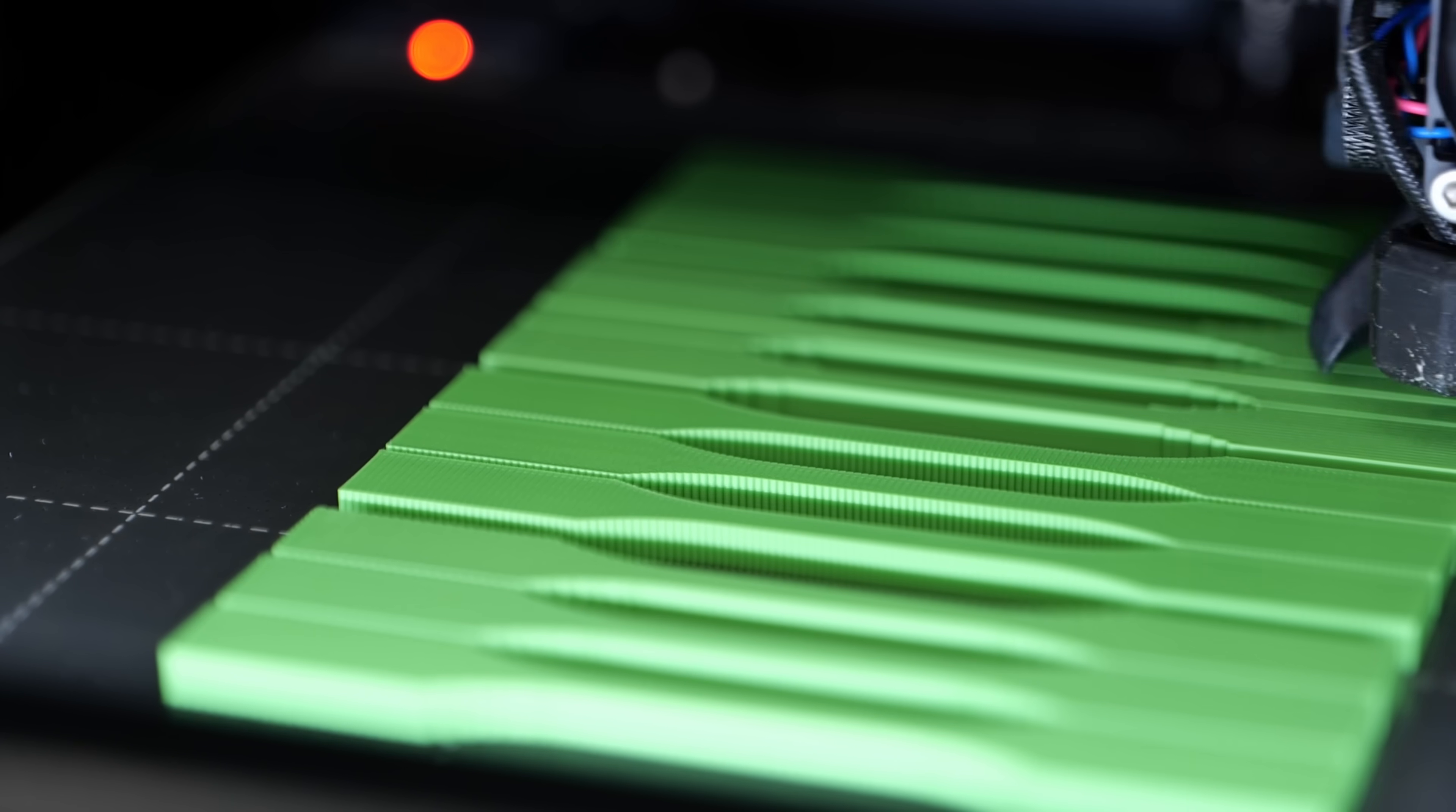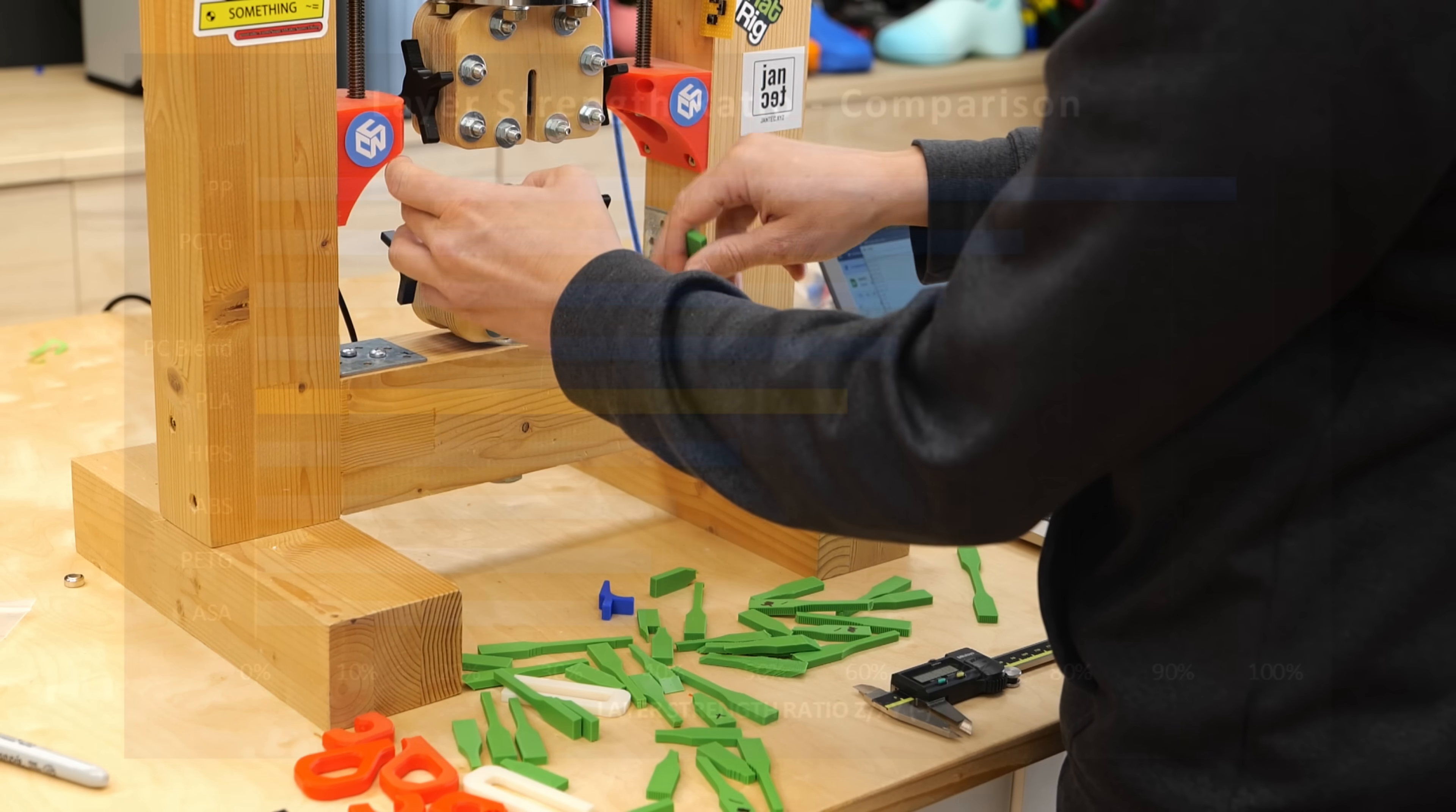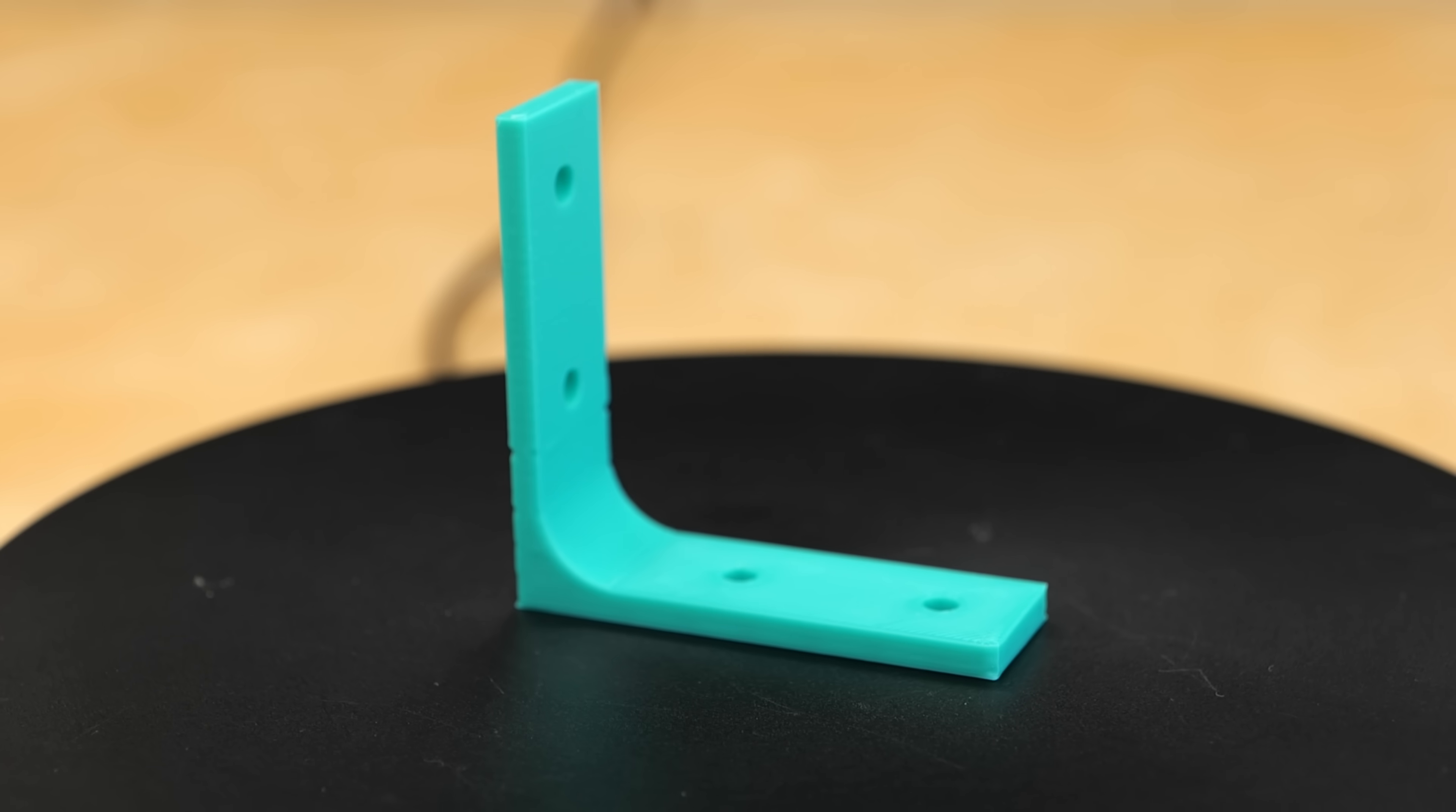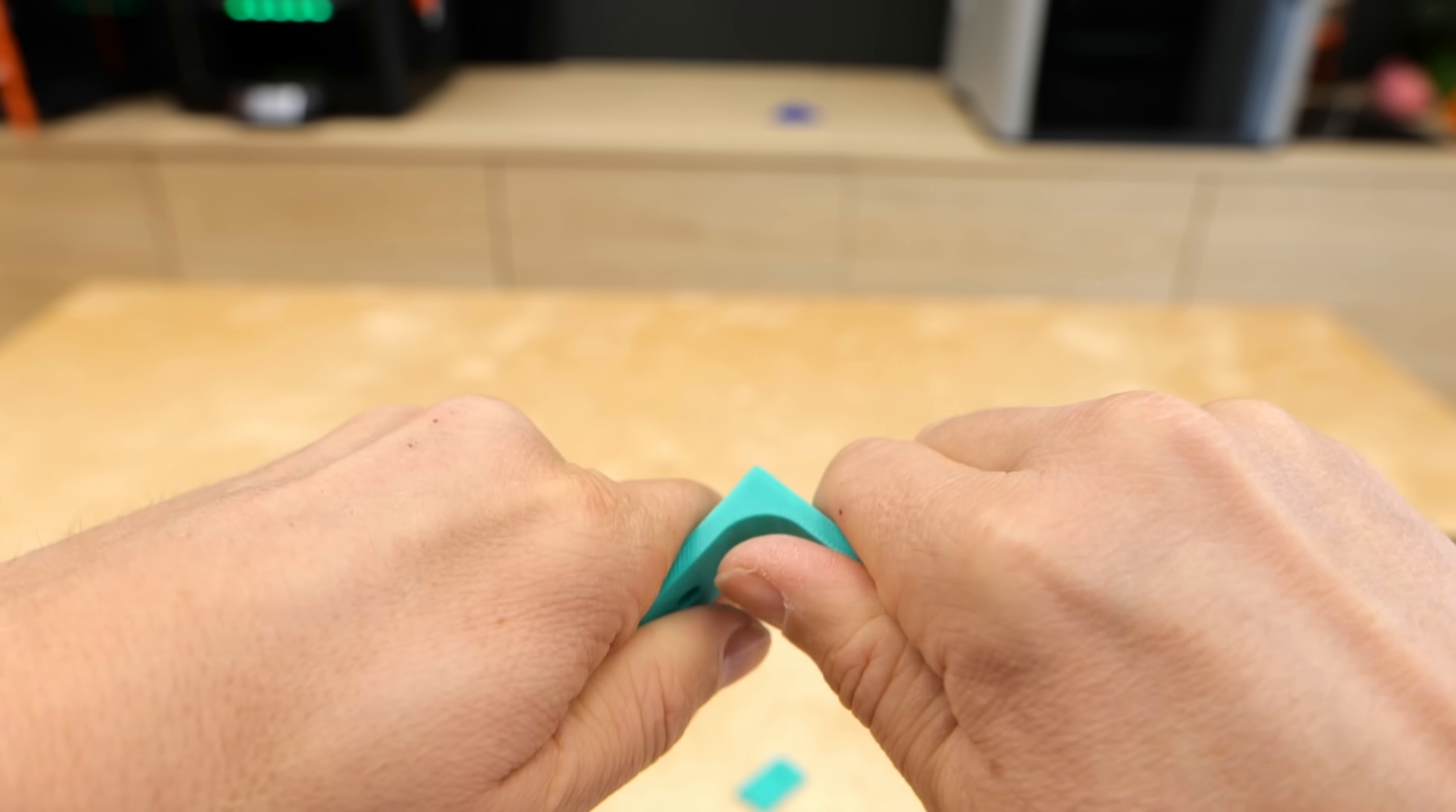Now back to the 3D prints. Depending on the material, printer and settings you use, layer adhesion is typically around 50% of the in-plane strength as we've just seen here. It can go much higher with some materials but also drops significantly if you, for example, print ABS with a lot of cooling. So to increase the strength of our bracket without redesigning it, we simply place it on its side so that the stresses when loaded are more aligned with the print lines, where the part is the strongest.